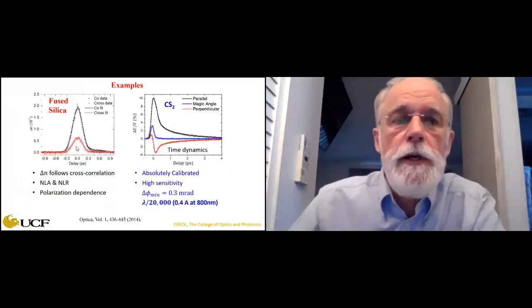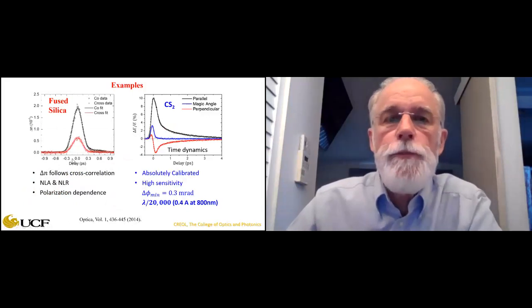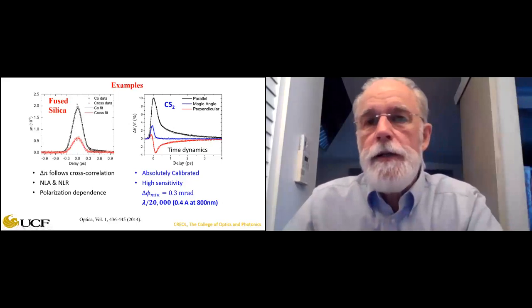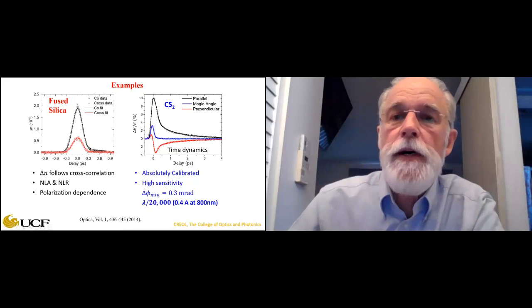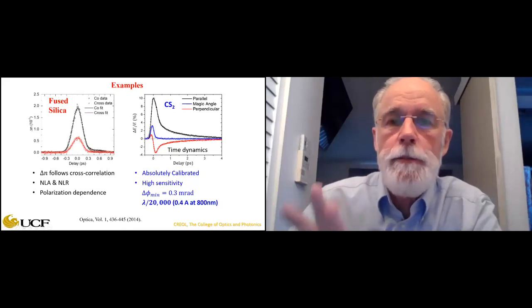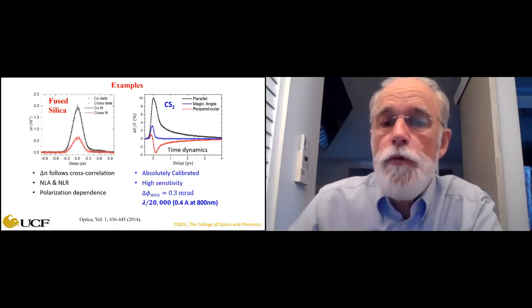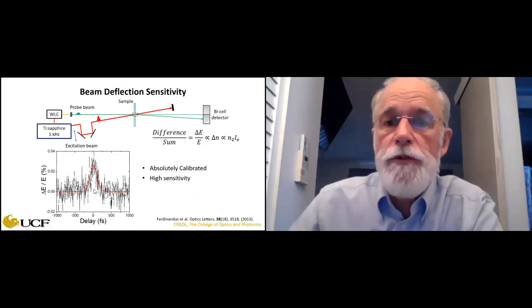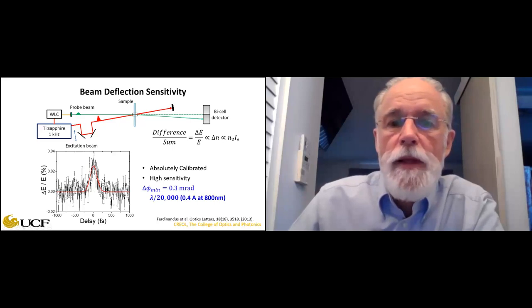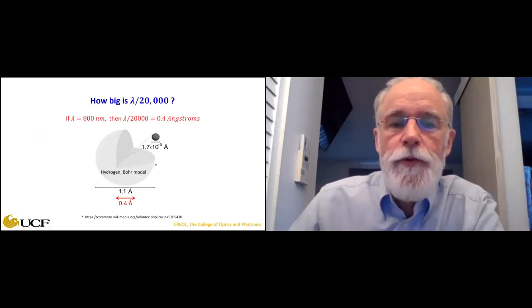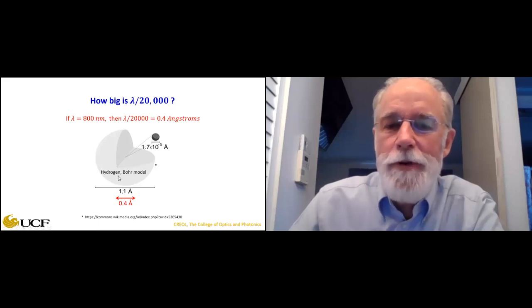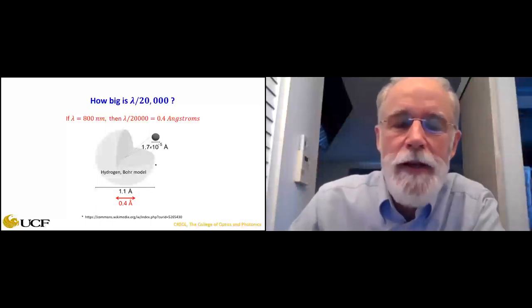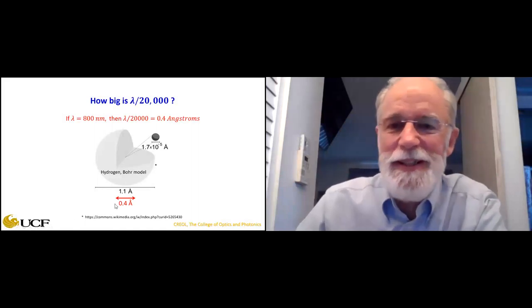Here's fused silica — and you can also look at the polarization dependence. Parallel polarization versus perpendicular: for a bound electronic chi-3 it should be three to one. You see three to one. We've been able to see better than lambda over 20,000 — that's 0.4 angstrom optical path length change, much less than the Bohr radius. Of course you're averaging over many, many molecules, so it's not as good as LIGO, but lambda over 20,000 is pretty impressive.